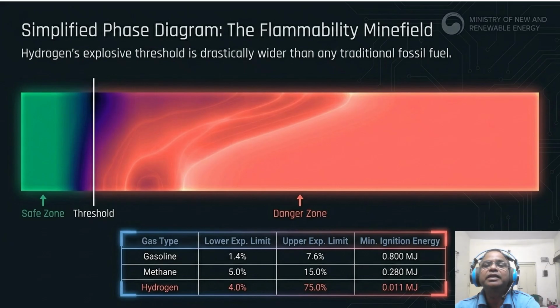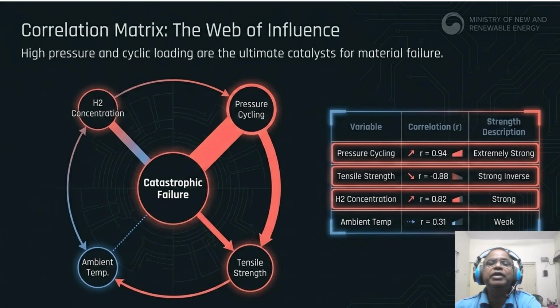So, to manage that environment, we have developed a correlation matrix to identify the ultimate catalyst for the failure. Coming to our next slide, which is about a correlation matrix, the web of influence. This constellation plot shows the factors leading to catastrophic failure. Notice the thickest red arc, that is the pressure cycling. It has a correlation coefficient of R = 0.94, as shown in the slide very clearly. So that is an extremely strong relationship.